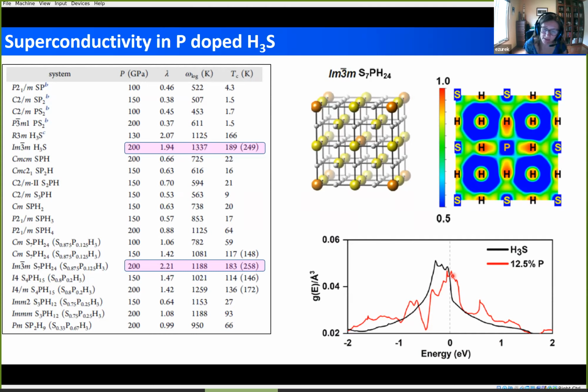If we look at the density of states at the Fermi level for 12.5% dopings of phosphorus, you do not see this type of reduction that we saw in our previous calculations on carbon doping. So we think that phosphorus doping, and potentially doping with other elements with similar properties to phosphorus, could also be very beneficial in exploring these systems.